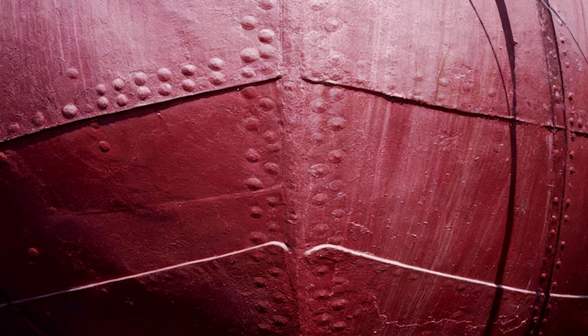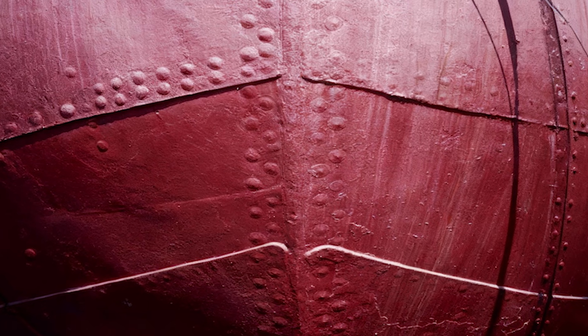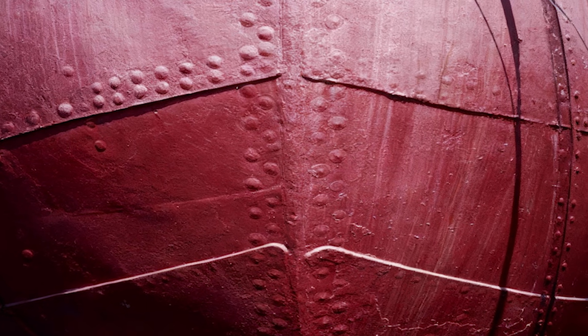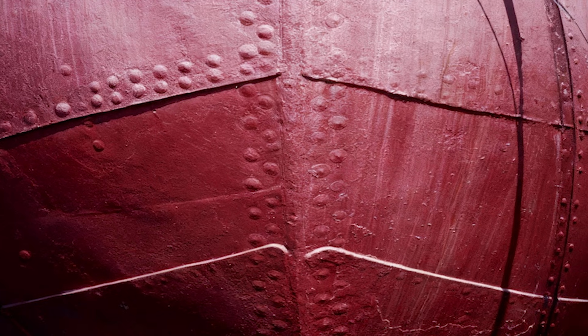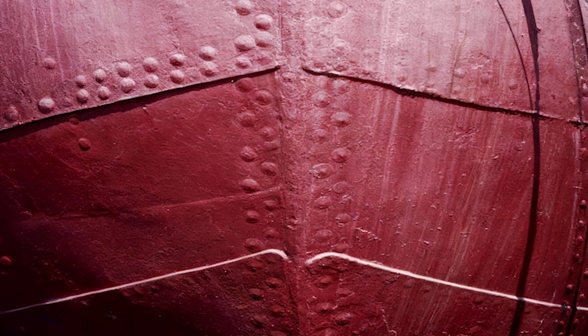The catastrophic failure began at the No. 3 cargo hold, where a stress concentration at a square hatch corner initiated a crack that propagated through solid steel plate at nearly the speed of sound. The fracture did not follow weld lines or joint boundaries. It cut directly through base metal that should have been the strongest part of the hull structure. Within seconds, the crack extended from deck to keel, compromising the structural integrity of the entire midship section.